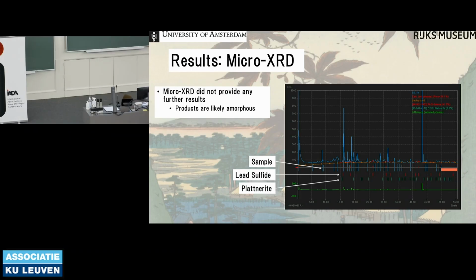Unfortunately, it was found that the micro XRD analysis did not prove any more effective than other XRD analysis, likely showing that the black, silver, and gray products formed are amorphous and cannot be detected using this method at all. Here's a graph showing that the two most likely products have little to no correlation with what I detected.